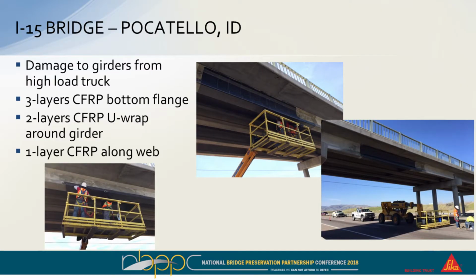2 other projects were done. These were a little bit different. This is an I-15 bridge in Pocatello, Idaho. This one was damage from an overheight truck, a high-load truck. Again, a lot of damage was done to some of the strands. And in this case, they are using a carbon fiber system because they had to restore some of the structural integrity of the material. The advantage of the pre-saturated system here is they had a very limited time to work with the materials.